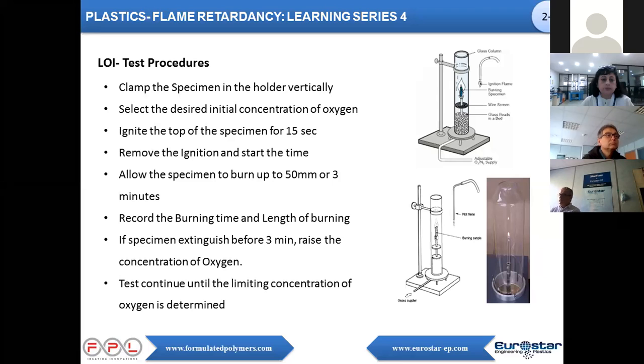The test procedure of LOI is simple and almost similar to the VB test. Here also the specimen is clamped vertically in the test stand. Using our similar products experience, the initial oxygen percentage is set. The specimen is ignited using a burner from the top of the column. Ignition time is 15 seconds at the top of the specimen. Remove the flame and allow the specimen to burn for 3 minutes or 50 mm length.